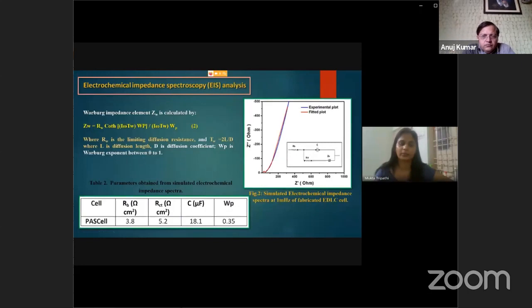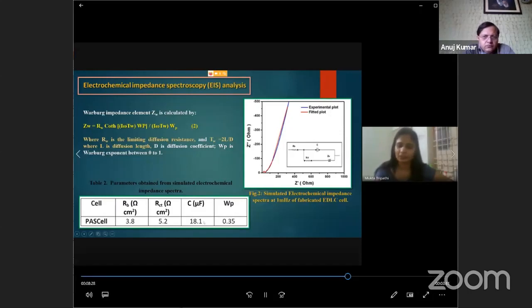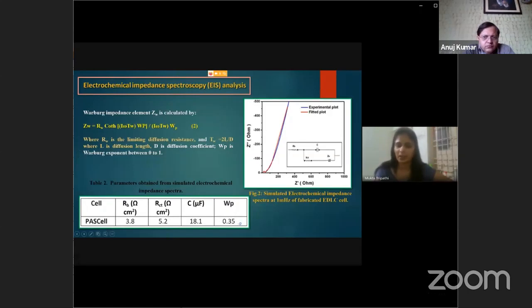This particular experimental data has been fitted using the ZView plot. By this we found the Warburg impedance, and that has been calculated using the equation shown here as equation number 2, and you can see there is good matching between the experimental and the theoretical data, and that equivalent circuit has also been shown in this particular diagram. So this is the simulated electrochemical impedance spectra, obtained at 1 millihertz for the fabricated cells. These are the parameters. You can see that RB is matched with the experimental technique. So that is the impedance.